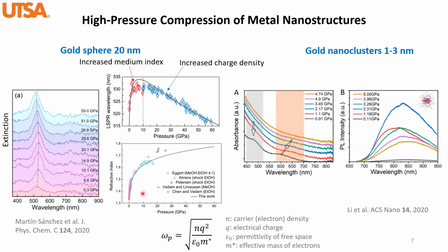I'm not really sure at this moment, but if it is still in liquid, it should still be fine. It's just a higher refractive index or a modified real part of the dielectric constant. Yeah, it's actually what we're expecting with the higher index. That means the propagation distance usually gets reduced. So we're actually fighting against this effect to have a longer propagation distance.